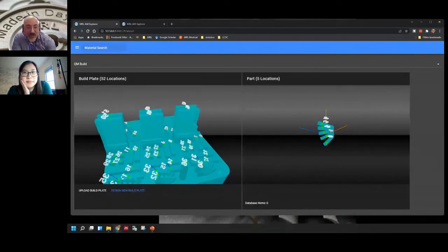That's an excellent question. Knowing the machine behavior, one of the questions said, can we apply that to AM? So we train the tools on the machine, and the training process takes only 1 or 2 build plates. And once we train the ICAM software on the machine itself, and we know the material, we have an ICAM database that takes into account microstructure evolution as a function of temperature, as well as the hierarchical simulation in interaction with SimuFact. From there, we predict location-specific distortion, which helps us later on to design the build plate and design the orientation, and predict the residual stresses in the as-built condition, and then later on after heat treatment, and if there is any need to consider during the machining operation.